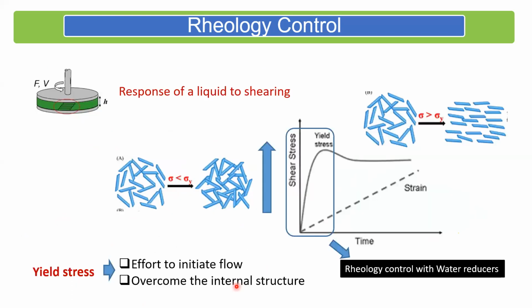So what are these rheological properties? Suppose I start shearing a fluid. Here is the fluid which is placed between two parallel plates. The bottom plate is fixed. The upper plate is rotated. So as I rotate the upper plate, I start shearing the liquid between these two plates, and I measure the response of the shear stress resistance that is generated in the material. If you do that, and I'm applying shear strain at a constant rate, so I'm shearing the material at a constant rate, what I typically get from cement paste looks like this.